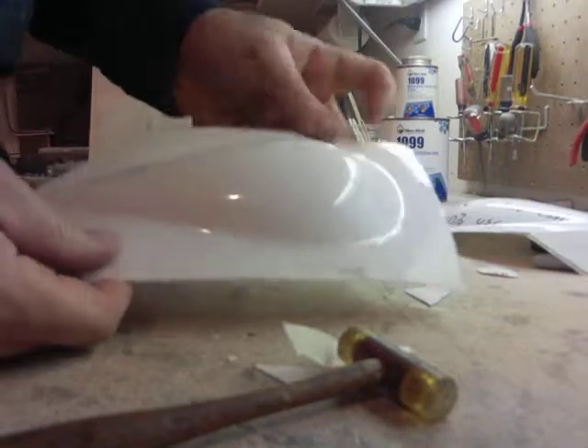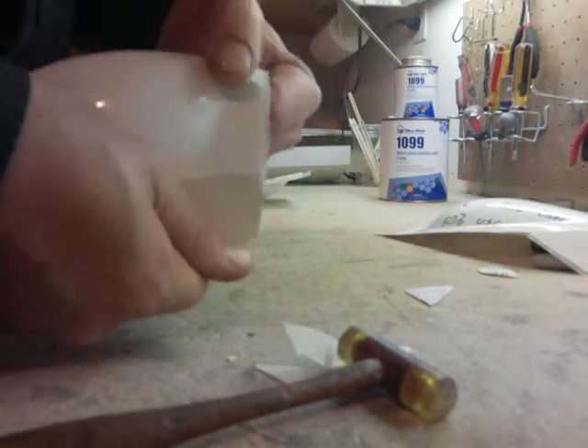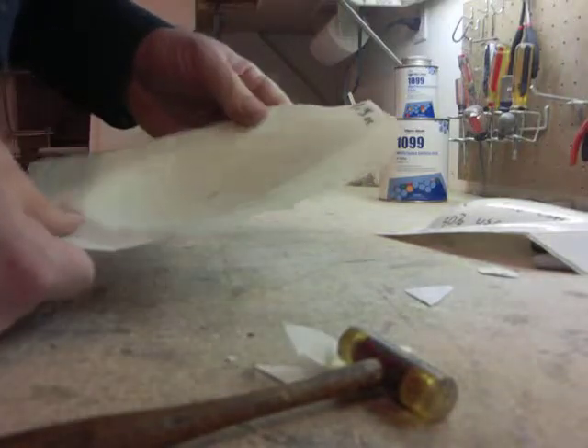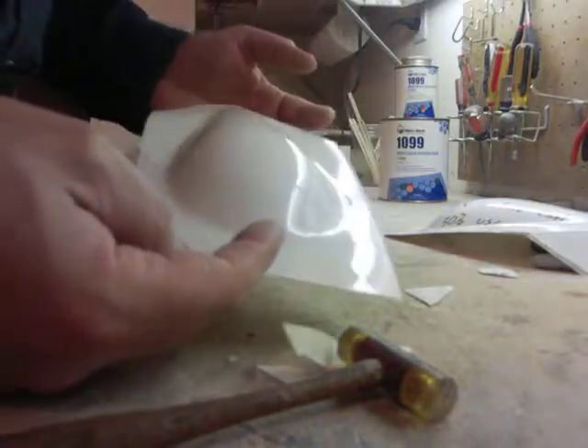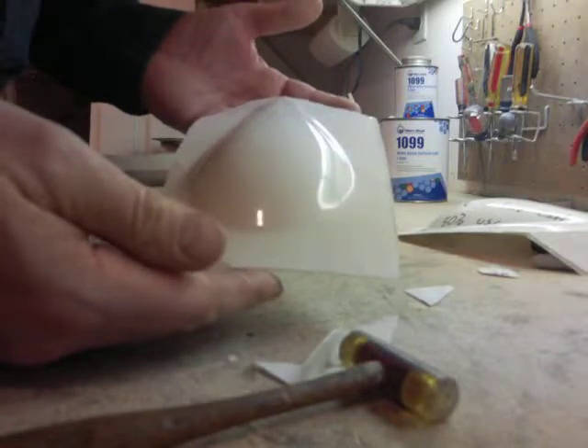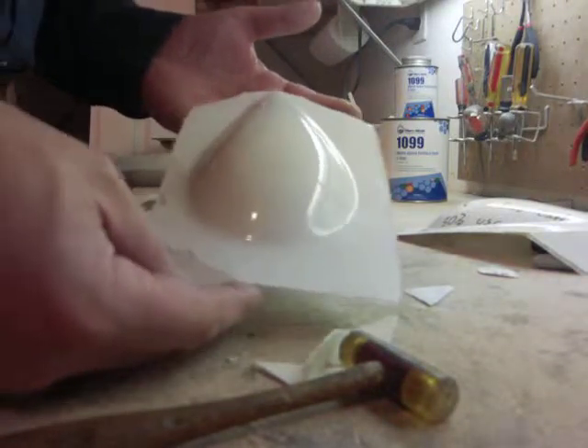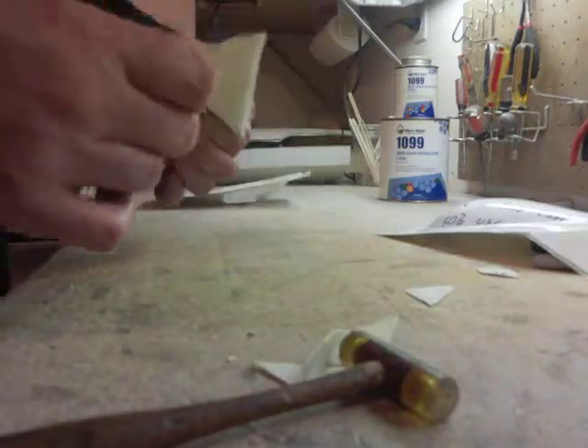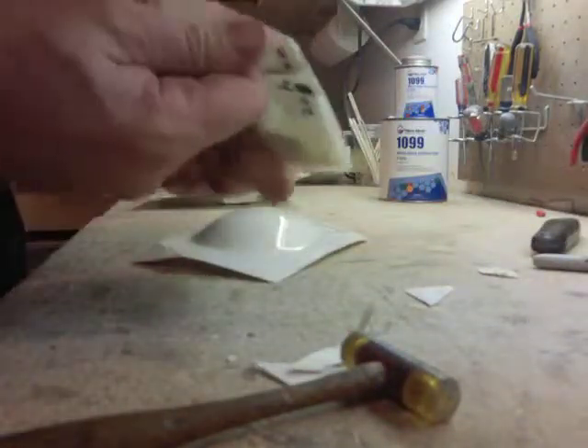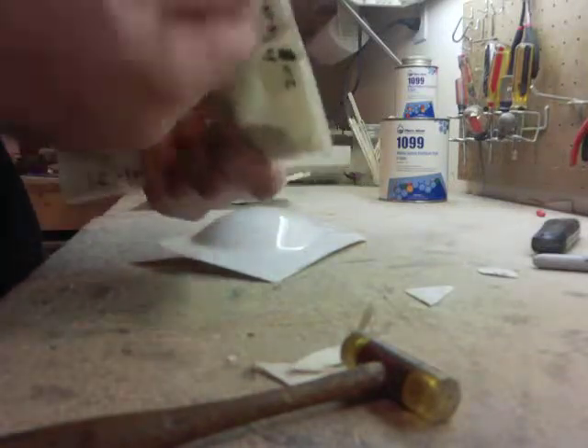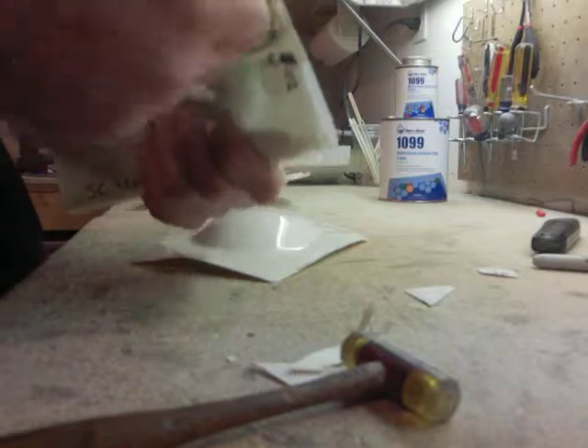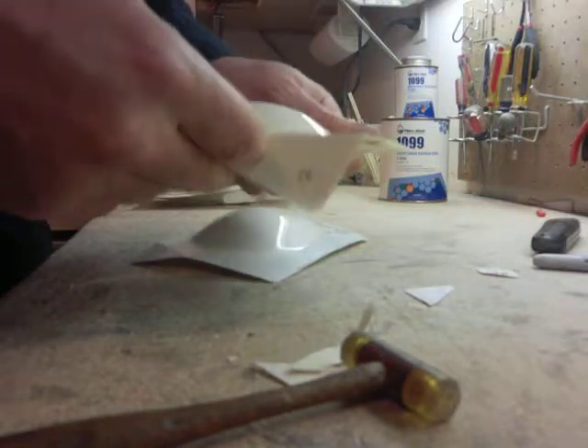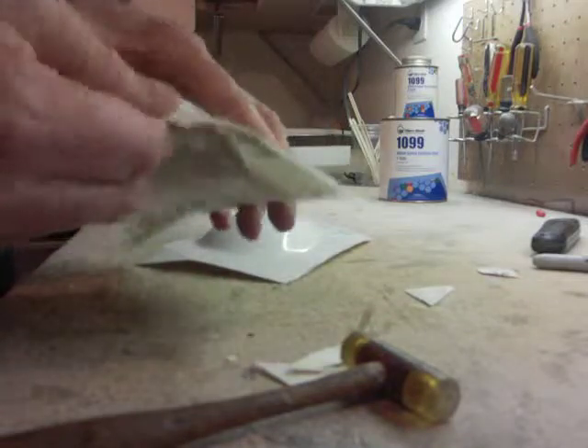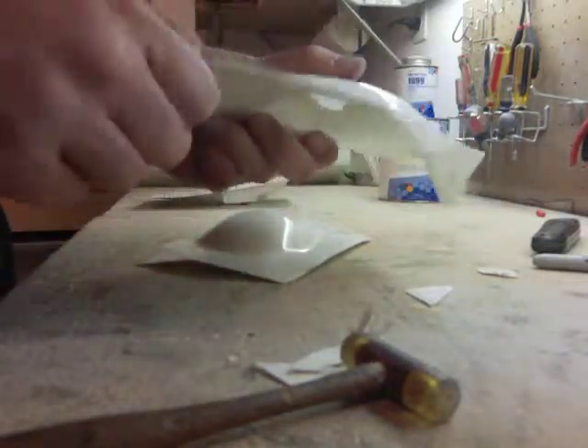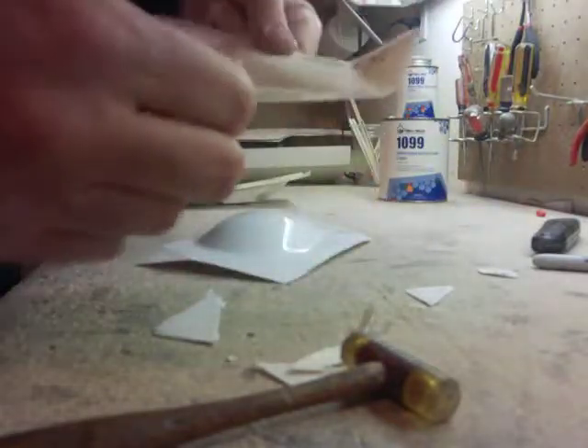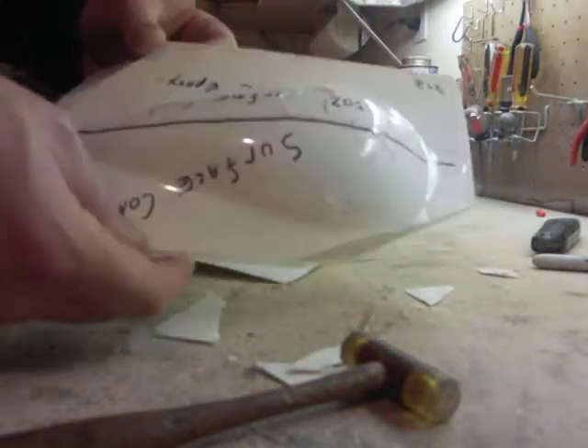Yeah, that one's actually, adhesion is real good. You can get the tooling coat to crack, and that's 2 layers of 4 ounce glass there with an epoxy tooling coat, thinned 20% with the epoxy laminating. Does not seem to have any ill effects to it. Here's the 100% surface coat, and if anything, it's actually maybe a little stronger, a little more rigid. But it cracks easier, so maybe this is a little more flexible just due to the epoxy laminating resin in it. Yeah, you can rip the glass right apart and the surface coat stays attached.